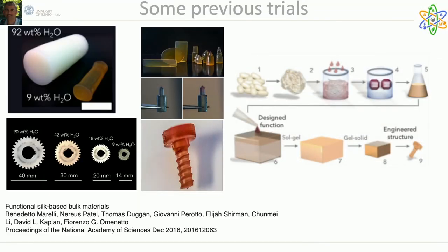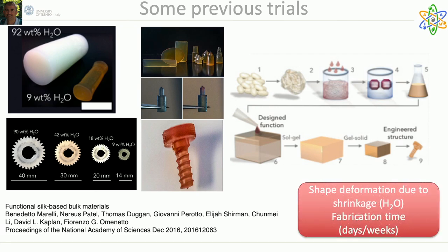Some attempts have been done in recent time from Marelli et al., starting from the idea of solution casting that allowed obtaining large monoliths. The two main limits of this technique were the large shape deformation due to the shrinkage caused by the water evaporation and the excessively long process time, since the complete evaporation can last from several days to several weeks, depending on the dimension of the monoliths.